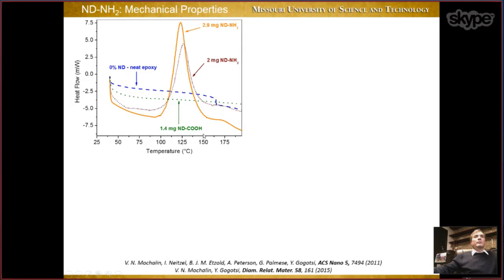And we do this experiment with two different kinds of nanodiamond. Well, first of all, we check pure epoxy with no nanodiamond. We heat it within this temperature range. Nothing happens, okay? So there is no heat evolved. There is a small step which corresponds to glass transition, but it's not due to chemical reaction. And this is expected because epoxy should not react with itself within this temperature range. Then we add COOH terminated nanodiamond, which is shown by green dots here, and also heat it within the same temperature range, and again, no reaction, no peak, no heat.